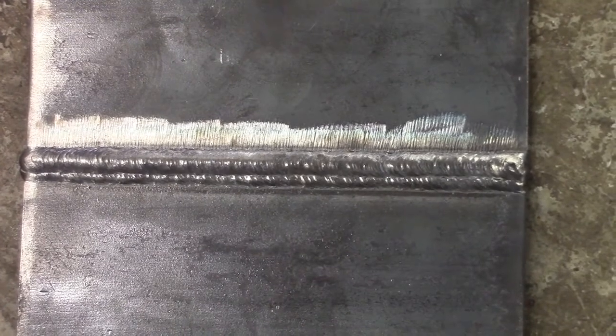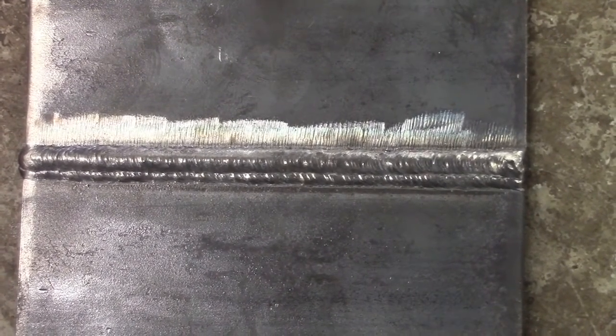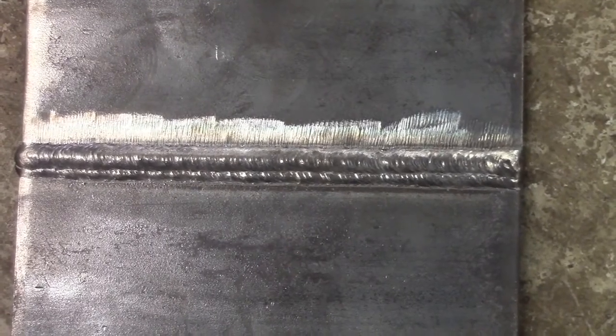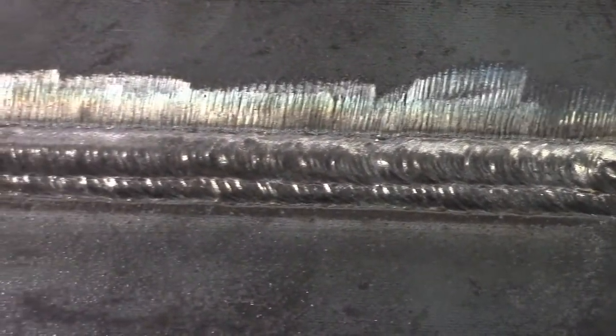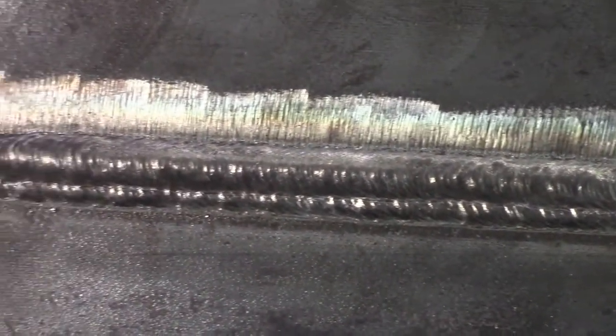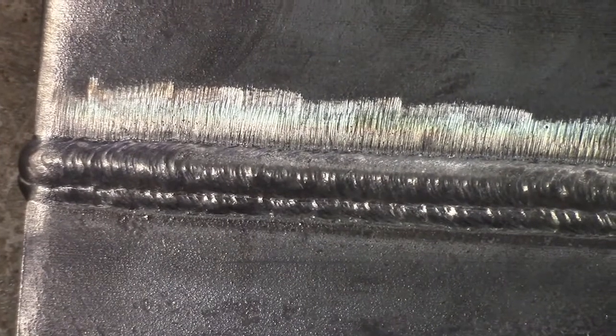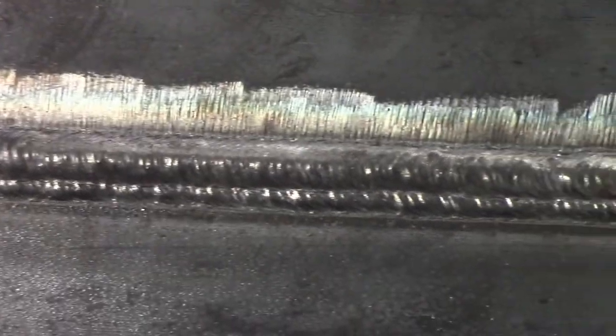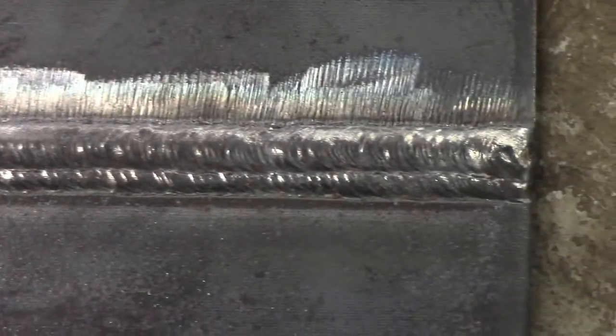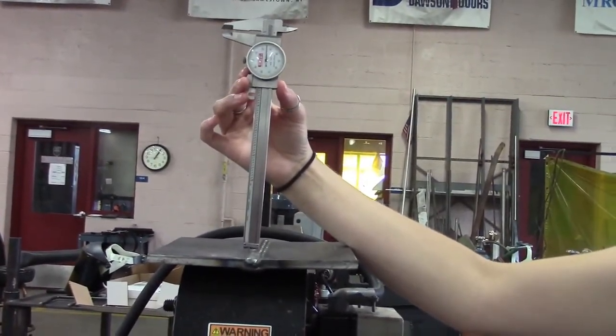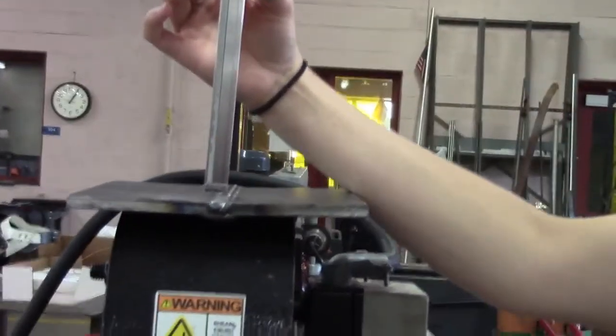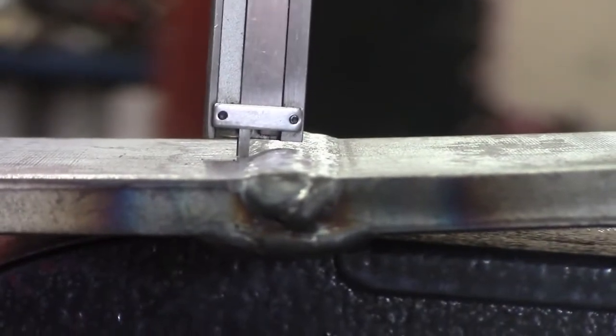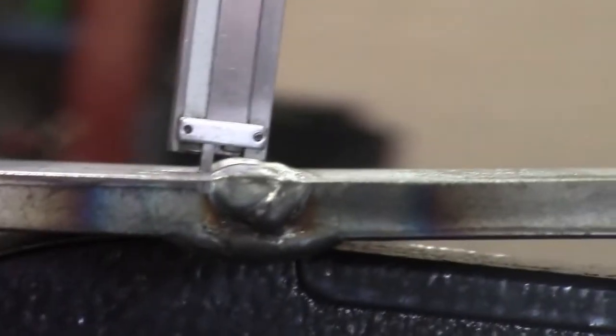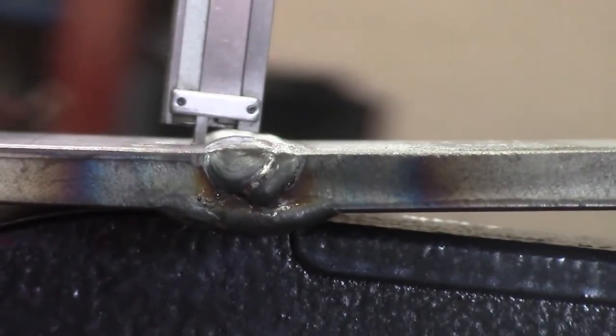Alright, this is the face of the weld we just did. You can see it looks pretty good. I'm going to try and get right down on it so you can see that there's nothing on there that'll not make it past a visual. Absolutely no undercut. Now what we'll do is we'll look at how high the convexity is, prove that it's not over 1/8 of an inch. So what we're doing here is we got a caliper and we just extended it out 1/8 of an inch so you can see the convexity requirement. Okay, there you can see it's well under 1/8 of an inch, so we're acceptable on our convexity.